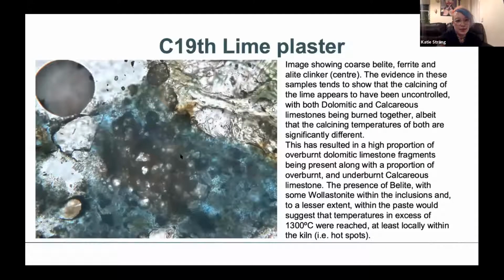And here is another image showing the cluster of belite. So the little white bits you can see are the alite, and the very dark stuff is your ferrite, and the rest is your belite that shows that kind of globular texture. And the evidence from these samples showed that the lime appears to have been uncontrolled when they were burning it. And where it is in the Northwest Highlands, we know that there is a lot of metamorphic rock there, which means that they were probably actually burning metamorphosed carbonates. So there would have been a mixture of both dolomitic and calcareous limestones being used.